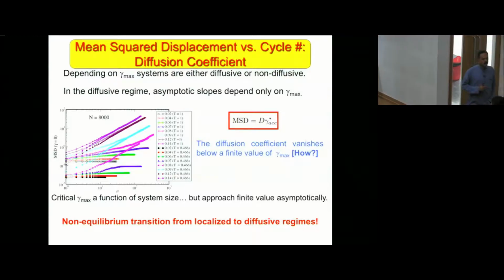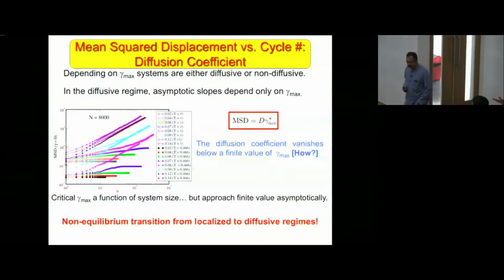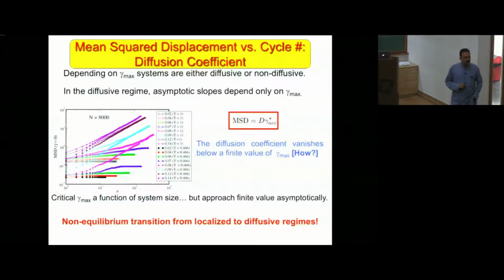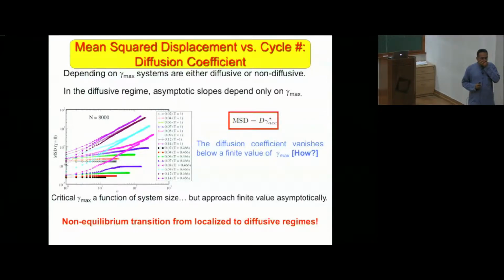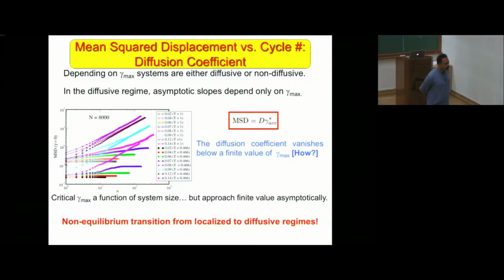Say what? So in crystals, when you do the shear cycles again and again, you have fatigue, but you always find that those become less stable, the more cycles you subject it to, it yields faster, right? Repeat that. So if you think of phenomena like metal fatigue, there what you're doing is you are subjecting the material to stress, then removing the stress, and what you find is that the material becomes weaker and weaker as you subject it to longer and longer cycles. The material fails much more easily. Right. But here it becomes stronger, right, in that initial regime.